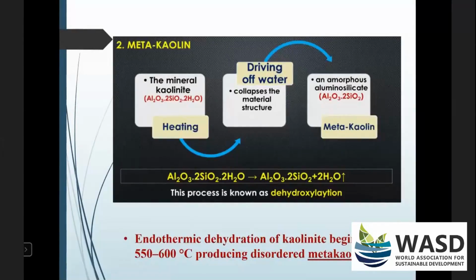The process of getting the metakaolin, which is the material that we are going to incorporate in our concrete mixtures: we had to treat the kaolinite clay in a thermal way. So it's a very simple and basic process where the mineral kaolinite is heated. Upon heating, this process drives the water off and collapses the material structure. The end result is an amorphous aluminosilicate, which is the metakaolin that we are trying to use in our concrete mixtures.